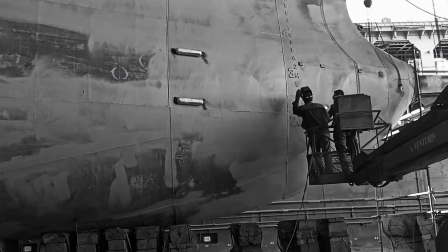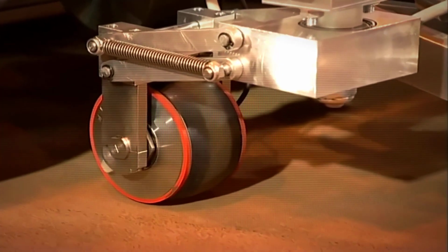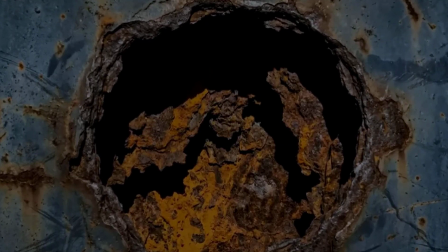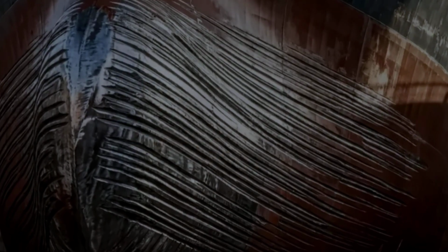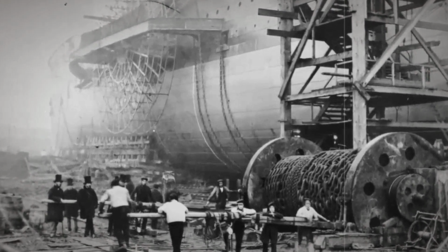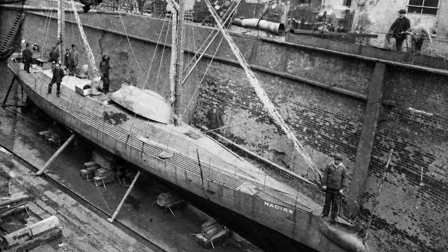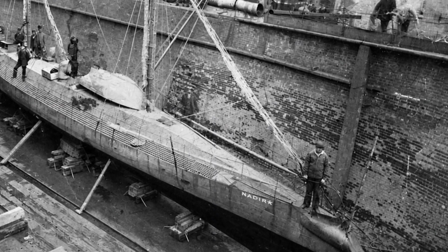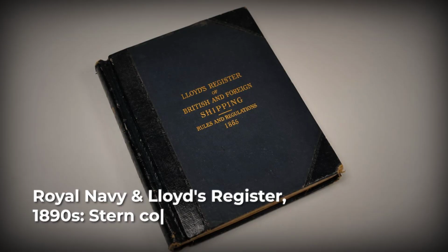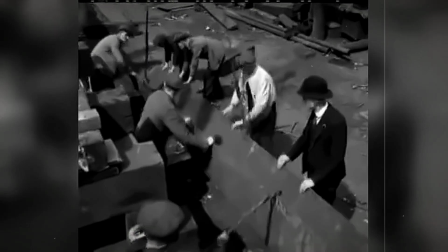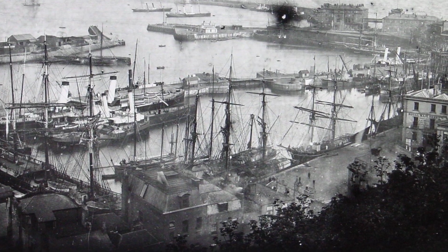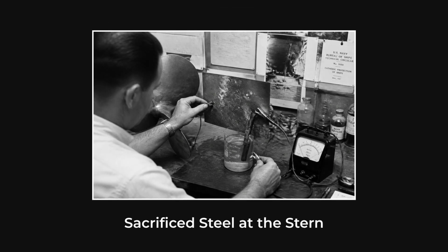But while this accidental battery spares the propeller, it introduces a severe threat to the surrounding hull plates, which now face rapid localized destruction. In the late 19th century, as shipbuilders transitioned to steel hulls while retaining copper alloy propellers, they quickly observed a localized pattern of destruction. Royal Navy technical notes and Lloyd's Register circulars from the 1890s documented severe, intense pitting concentrated almost entirely around the stern. Steel hull plates, rudder fittings, and structural rivets adjacent to the bronze propellers were degrading at rates that defied standard wear models. The electrochemistry of the marine galvanic series explained the mystery.